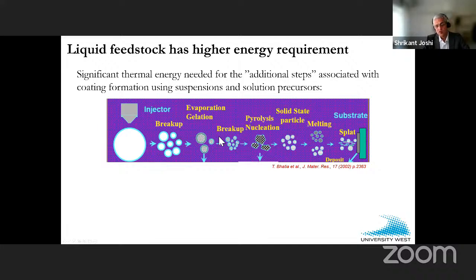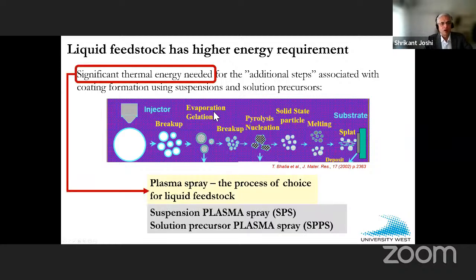What you see on this cartoon is from a publication very early on when people started looking at solution precursors, right? A lot of things need to happen for the precursor to get through gelation, then pyrolysis, then hopefully the powder of interest is formed in situ. And then this powder from this point on behaves like one would expect: melting, acceleration, formation of splats, right? But all of these steps require significant thermal energy.